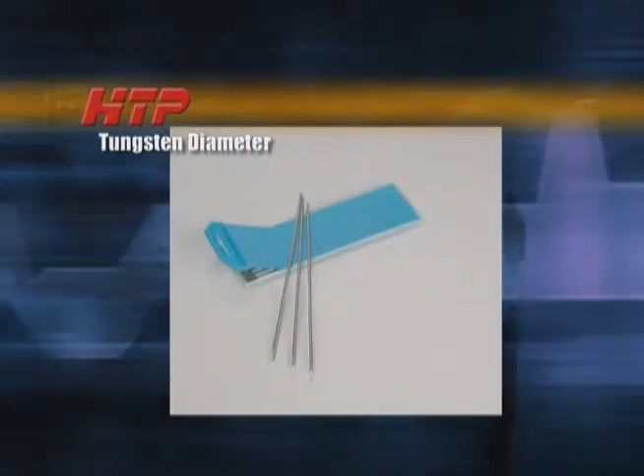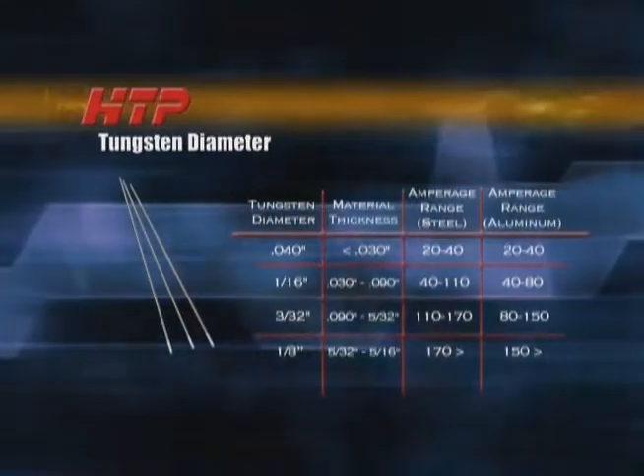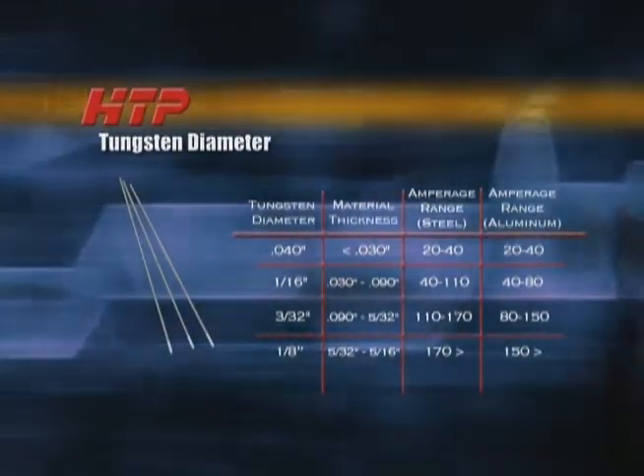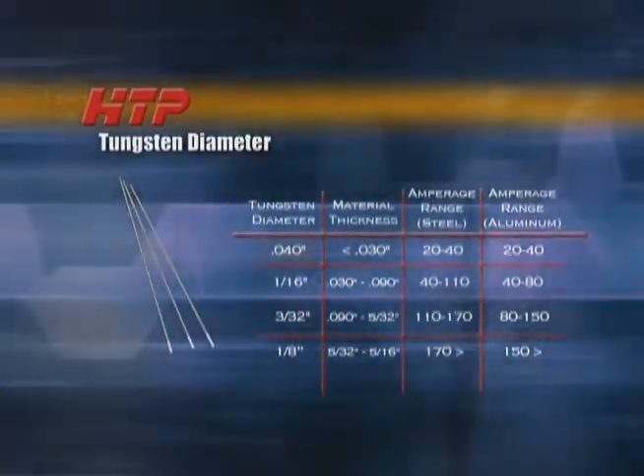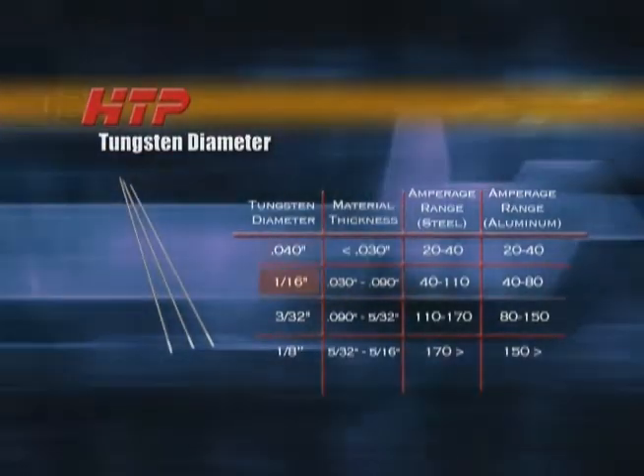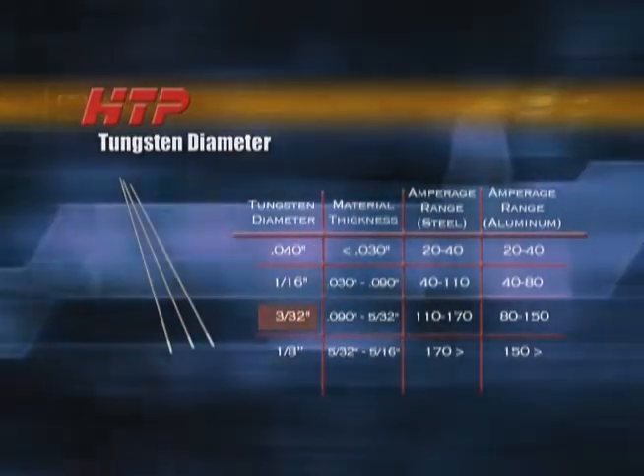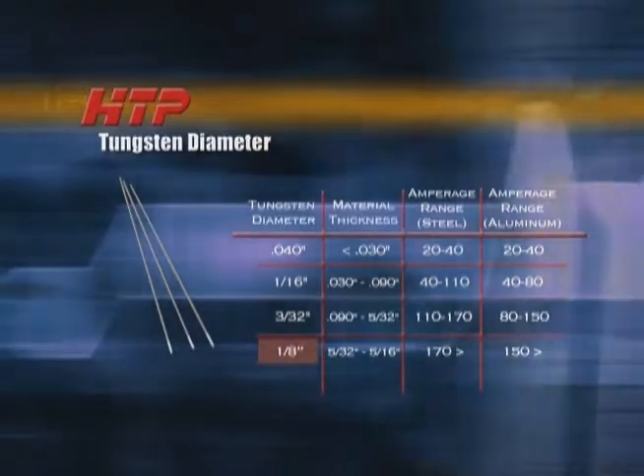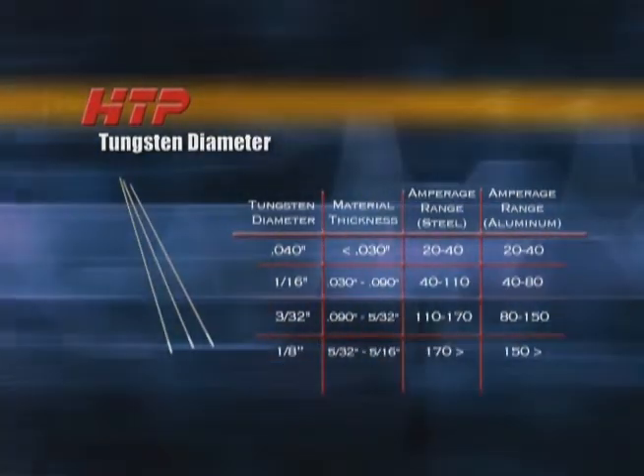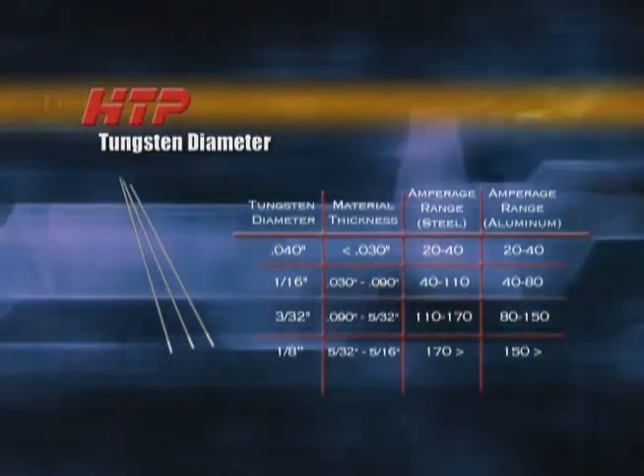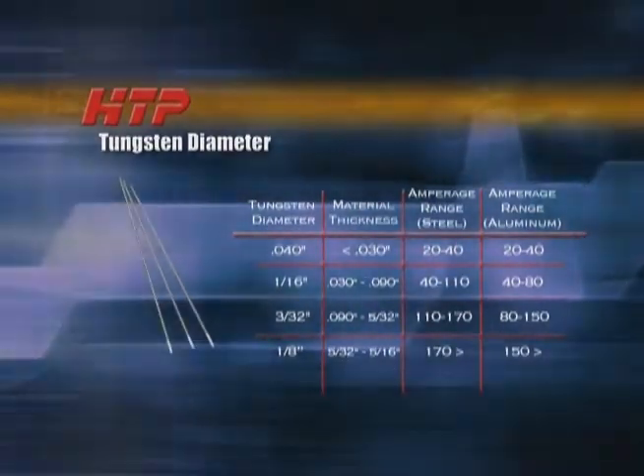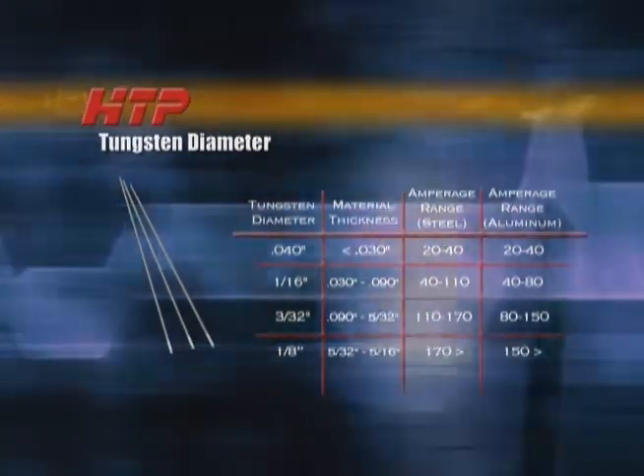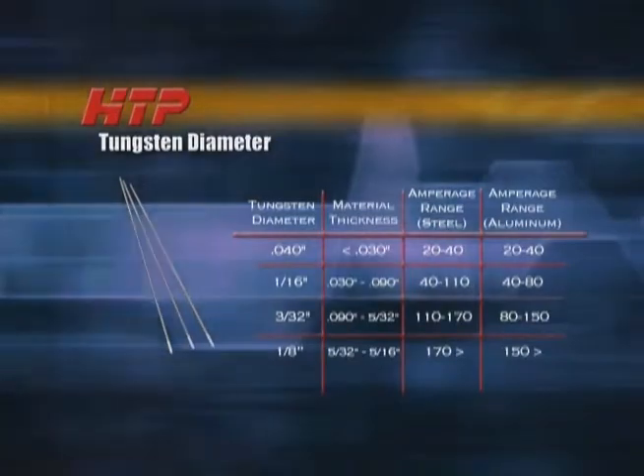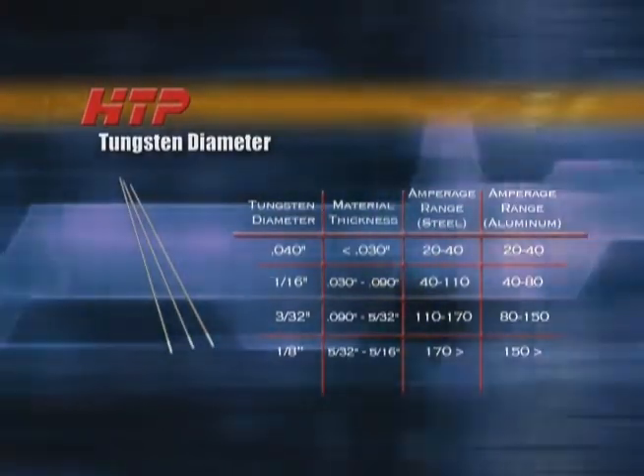Now that we have talked about different types of tungsten, let's look at the different diameters. Generally, there are 4 diameters to be concerned with when using a 200 amp welder: 40 thousandths, 1/16, 3/32, and 1/8 of an inch. The thicker the material you will be welding, the larger the diameter of tungsten you will use.